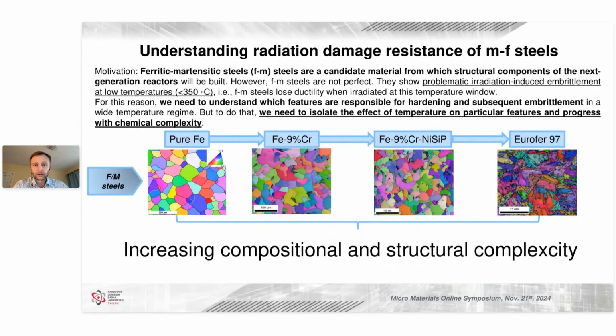So first, ferritic martensitic steels, which very often means Eurofer 97, are considered as a candidate material for structural components of the next generation nuclear reactors. However, these steels are not perfect. They show problematic irradiation-induced embrittlement, especially at low temperatures, and loss of ductility. Therefore, we need to understand what happens with these materials at low temperatures.